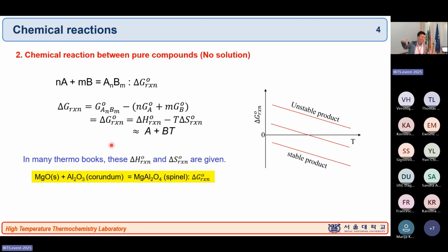When it's always positive, it means you cannot make your product, yeah? Because your Gibbs energy of reaction is positive. So it means your reactant is stable. And when you have the curve on the bottom, it means your reaction Gibbs energy is always negative. It means you can always produce your product thermodynamically, okay? And sometimes we have something in the middle, so it means depending on the temperature, we may form or we may not form, okay? But this is all considering the pure standard state without the solution state, okay? So this value, you cannot change it. This is determined by nature itself.